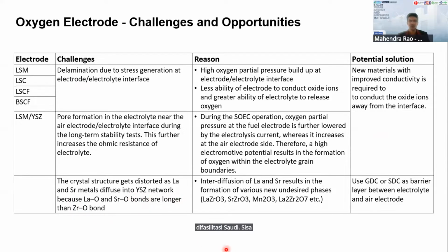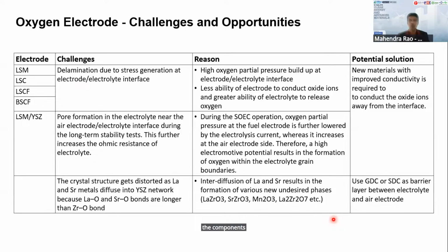And then again, the crystal structure gets distorted as the lanthanum and strontium metals diffuse into the YSZ network. So this is the structure change. Due to the interdiffusion issue, as I highlighted before, this is another solution. That's the reason why they use a barrier layer such as GDC between the air electrode and electrolyte to mitigate this interdiffusion issue. So these are common challenges that we find in most of the components in solid oxide fuel cells, for the three principal components.